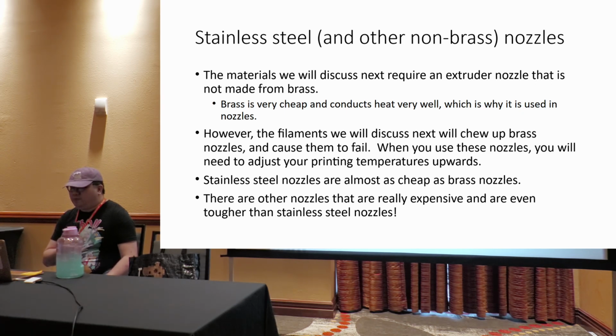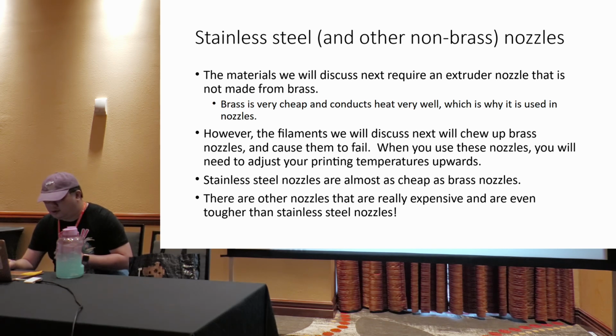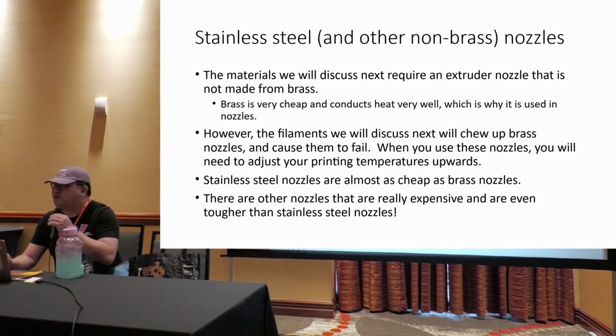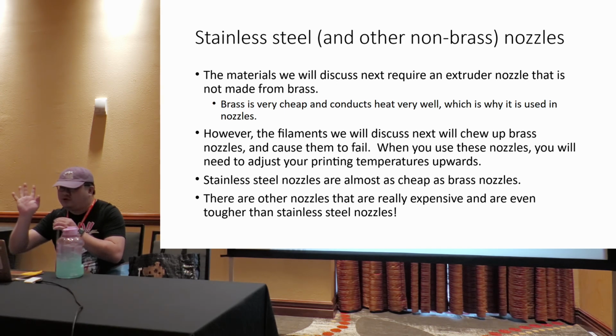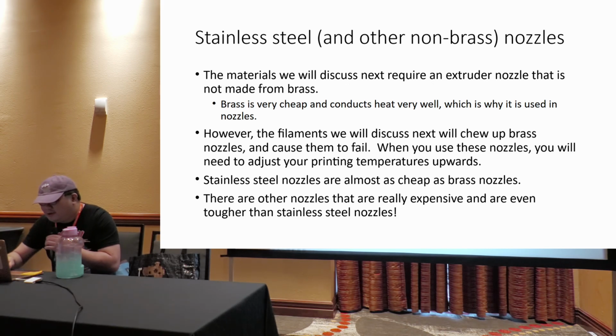Now, the reason why they use brass is because it conducts heat very, very well, and it's really cheap. So basically, get a stainless steel or a not brass nozzle, and when you print with these, probably up your temperature by about 10-15 degrees Celsius because these other nozzles do not conduct heat as well. You definitely don't need ruby nozzles. Trust me. If you know how to replace the nozzles, just use stainless steel. All right.